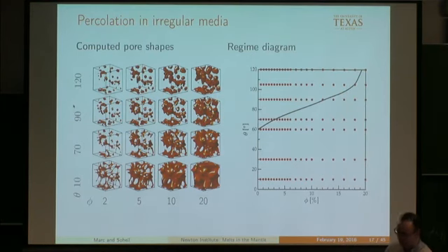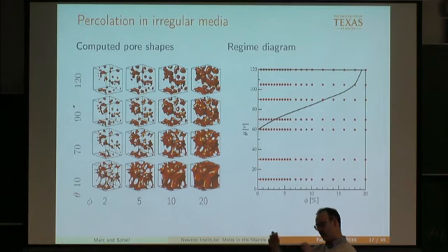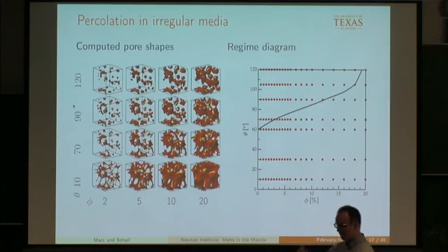And the reason, if you think about it afterwards, is sort of pretty obvious, because in the regular medium, all the pockets are separated by exactly the same distance, and they all touch at exactly the same time, and everything connects. In an irregular medium, all the grain edges have all different lengths, and of course the two pockets that are closest together touch first, and then it percolates, so to speak, up successively larger grain edges get connected.